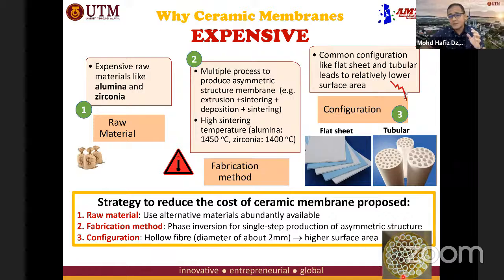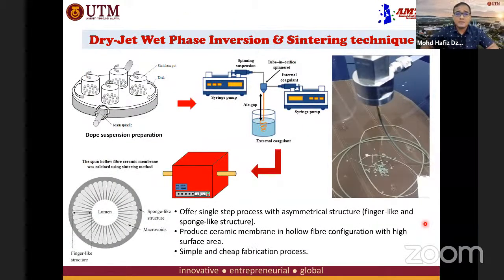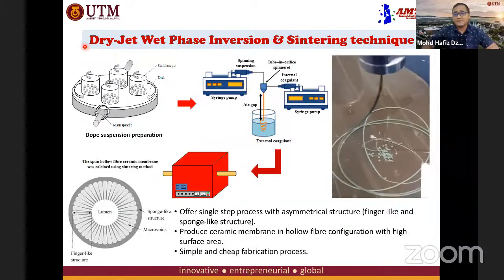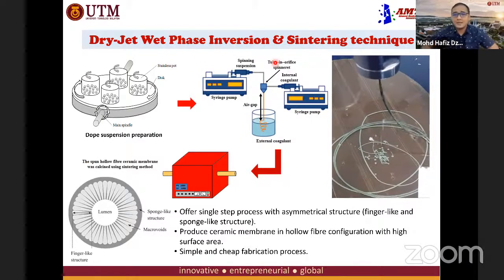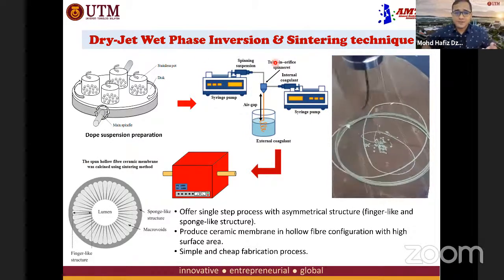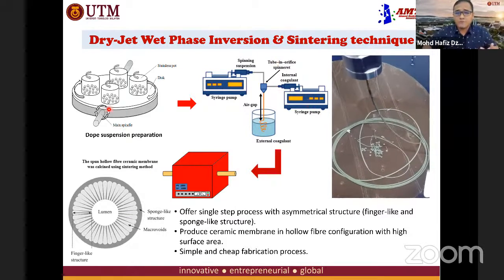This is some picture of the hollow fiber. The diameter is about 2 millimeters, and we can increase the surface area of the membrane by having this type of structure. So this is the dry jet wet phase inversion sintering technique. Okay, the technique that is now emerging to produce the hollow fiber membrane.